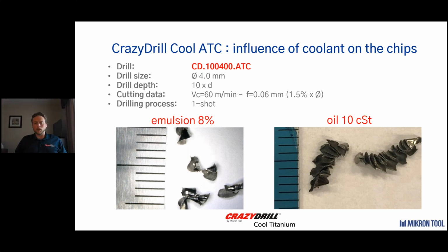When it comes to type of coolant, this is an example. It's a case study with a 4 millimeter version of our ATC, drilling in grade 5, one shot, where we were able to look at 2 different types of chip formation. On the left, we see an emulsion. On the right, we see an oil. Typically, oils lubricate better. Water-based evacuate heat a little bit more.